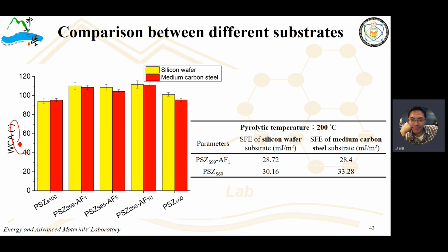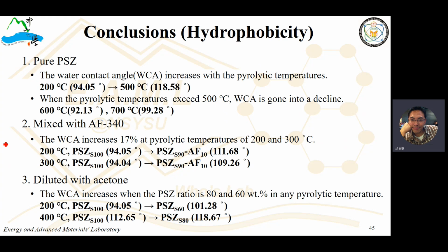Even the water contact angle and the surface free energy show no big difference. Therefore, I can say that, in all probability, it works for different substrates, metals or silicon, glass, and so on. So the conclusion is that for the pure PSZ, the pure pre-ceramic precursor, the contact angle increased from 94 to 118.58 with increasing cross-linking or pyrolytic temperature. When this temperature is higher than 500 Celsius, the contact angle drops.